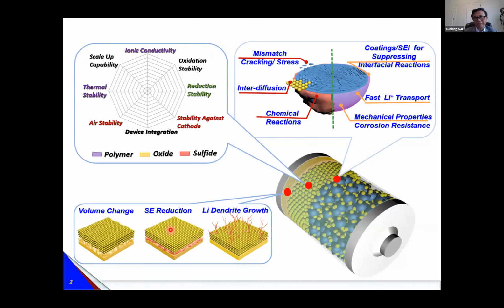So when we talk about the solid-state electrolyte, we know currently we have polymer-based, oxide-based, and sulfide-based. If we compare different properties, for example, ionic conductivity, air stability, and reactions with anode, cathode, and the devices, all these factors, they have advantages and disadvantages. For example, for the polymer-based, the room temperature ionic conductivity is relatively low. And oxide is ceramic, so when you make devices, the interface is a problem. And sulfide has a very high ionic conductivity, but regarding air stability or reactions with anode and cathode, they still have a challenge. So that's why maybe we also need to develop either a hybrid, combining different electrolytes, or develop other types.